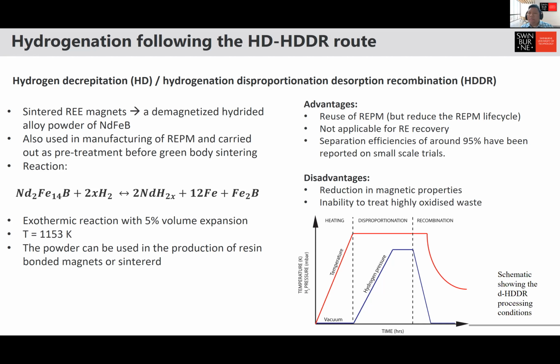Once you have a cast NdFeB mixture in the process, you react it with hydrogen at high temperature, and what happens is the hydrogen reacts with the neodymium, forming hydride. Now this is quite an exothermic reaction, and it is also accompanied by 5% volume expansion. So what happens is when it reacts, it actually crumbles because there's enough volume expansion. It becomes powder, and in the end you have this NdH2.